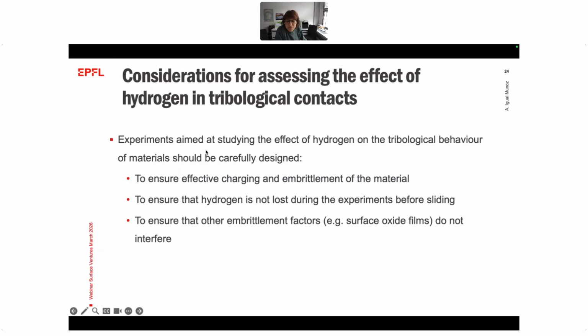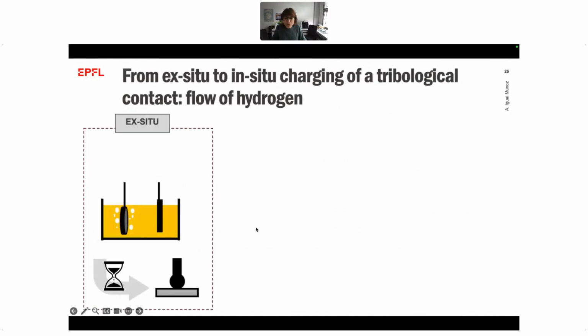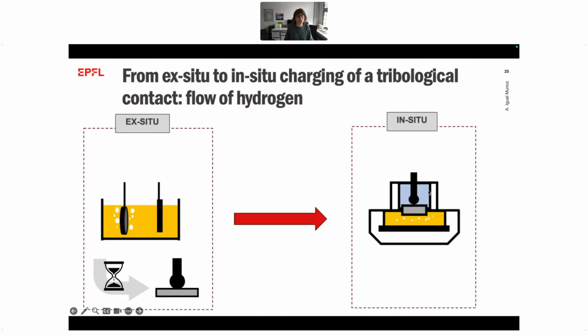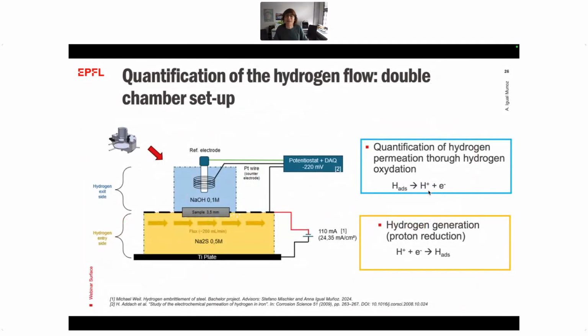We say, okay, whenever we design an experiment to assess the influence of a hydrogen atmosphere in my material, in my machine component, we have to ensure this effective charging. We have to ensure that hydrogen is not lost during the experiment, and we have to be sure which other factors that cause embrittlement are considered. So for that, we went from an ex situ experiment, where we charge and then do the tribological test, to an in situ conception of the testing conditions.